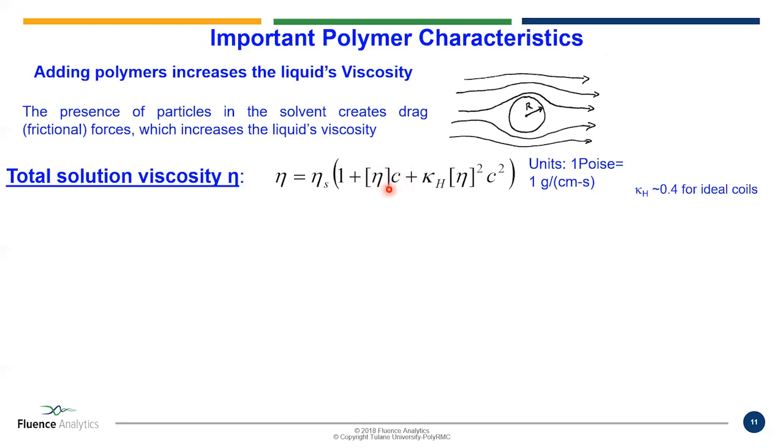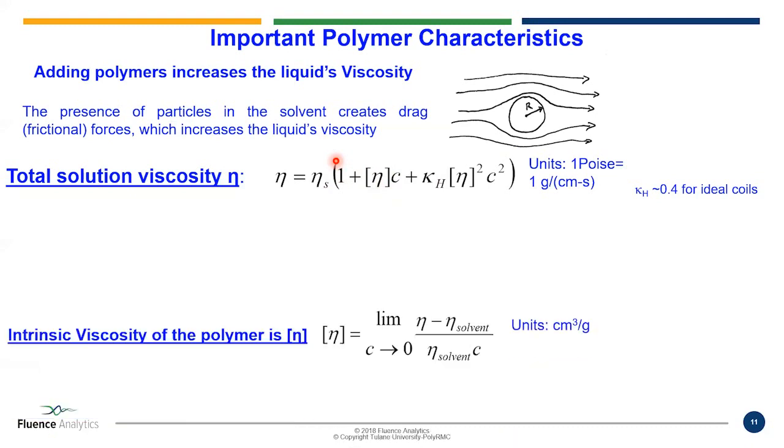This is called the intrinsic viscosity, this eta in brackets. So that's a single polymer fundamental property. It's very useful for understanding the architecture and other properties of the polymer. So we want to look at that a little bit more. As you start concentrating your solution, then the polymers start to interact, and you get the C-squared terms with some kind of a hydrodynamic interaction and so on. But we'll be down here dilute enough, as I said today, that we can just worry about this term here.